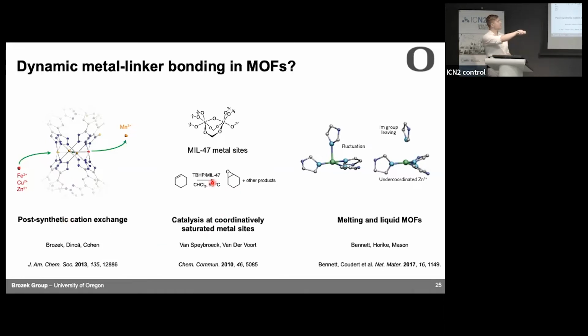There's also a lot of really nice catalysis work where the catalysis involves, and must involve, the substrate binding to the metal site, but this is often reported at MOFs like MIL47, where there aren't any open metal sites on the metal. And so sometimes it's probably defects, but in this particular case with MIL47, this is a really nice set of papers that showed pretty convincingly that rather than defects, it's actually dynamic linker metal bonds that allow the substrate to come in and get oxidized. Another popular area right now is melting MOFs and liquid MOFs. And when people talk about the mechanism of how a MOF melts, they already talk about these dynamic metal ligand bonds. So this is an important concept, but there's not a lot of evidence to actually show that it happens.